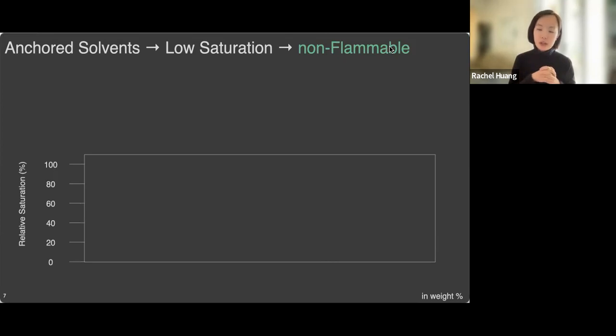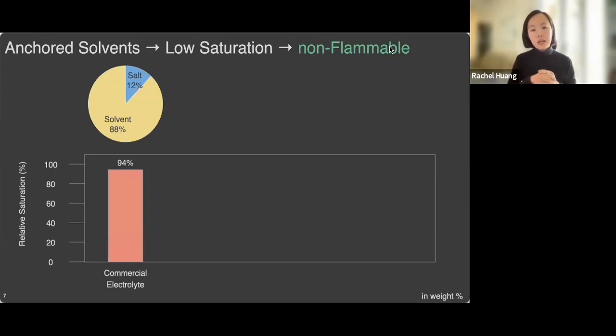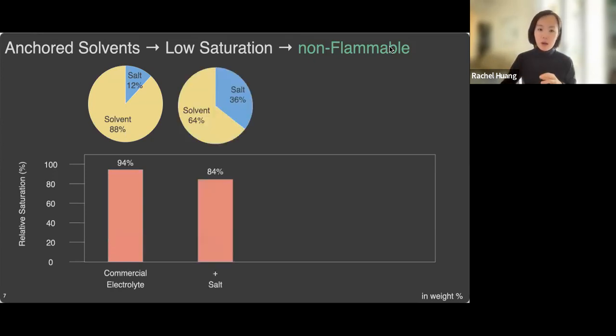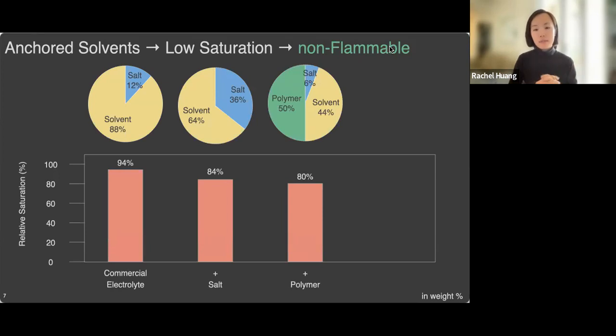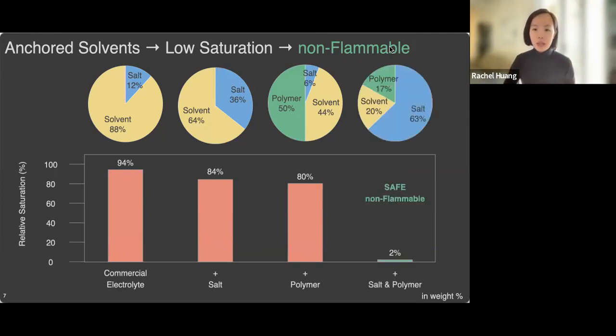We can measure the relative saturation of solvent molecules in different electrolytes. For the commercially available electrolytes, the relative saturation is quite high, which makes that electrolyte flammable. When we add more salt into the system, we lower the relative saturation, but it's still quite high and flammable. Adding more polymer into the system, we continue to lower the relative saturation. However, the electrolyte is still flammable. In our unique formulation of SAFE, we have 63 weight% salt and some polymer in the system. Our SAFE electrolyte only has 2% relative saturation, and it's no longer flammable.